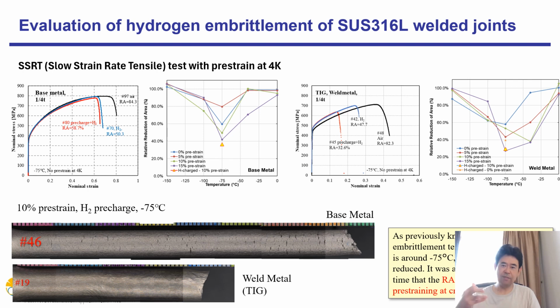So this is a simulation of the earthquake, and the temperature is the liquefied hydrogen temperature, 20K. If an earthquake occurs, part of the tank is subjected to plastic strain at 20K, so martensite transformation may occur. Results at minus 75 degrees C are shown here. This graph is base metal and this graph is weld metal. RRA is the main evaluation index. RRA of the SSRT test decreases much with pre-straining.